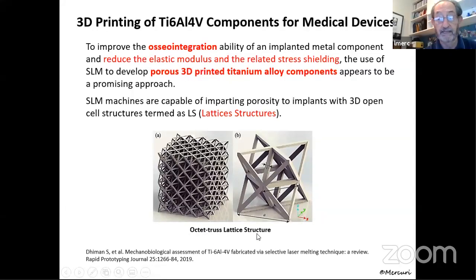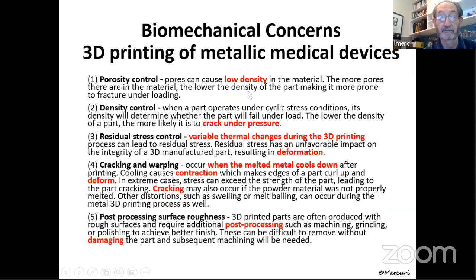This is an octet-truss lattice structure. This is obviously a much larger device, but you want to improve osseointegration. That's what everybody's after. Reduce elastic modulus and related stress shielding. So you develop a porous 3D printed titanium alloy, which is this. That's what you're after. And that's a great idea. The problem is that these pores, depending on their size, create a low density material. Low density materials tend to crack under pressure.